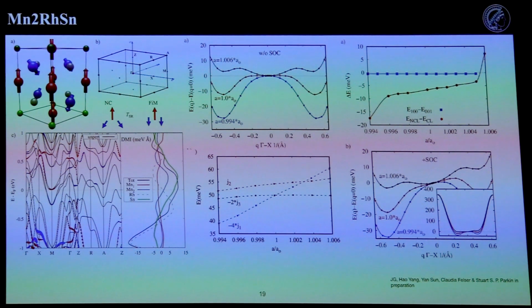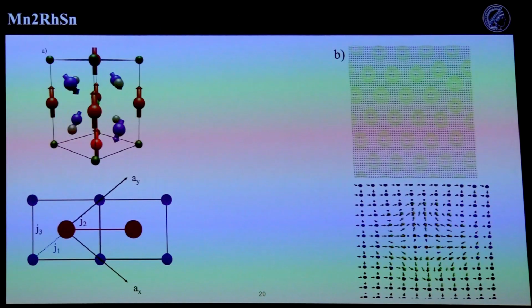When it's negative, it's in plane. So it's very weakly in plane, but it doesn't change as a function of strain. And then you also have things like the DMI, which also does not change as a function of strain. Then we said, okay, let's do some LLG equation type things.